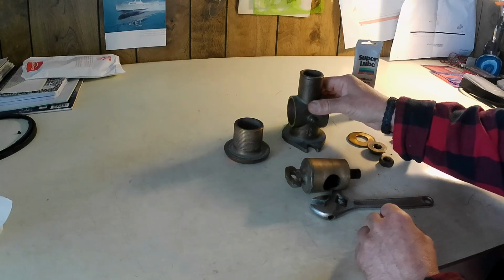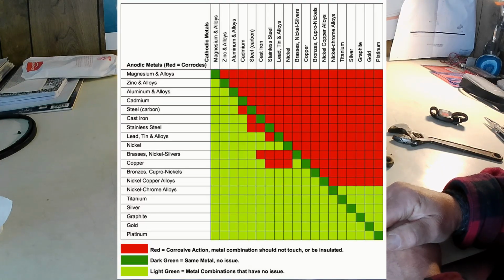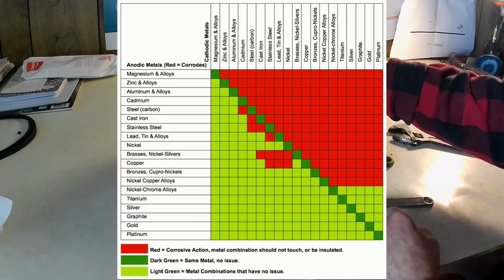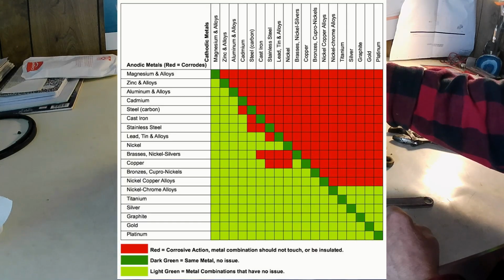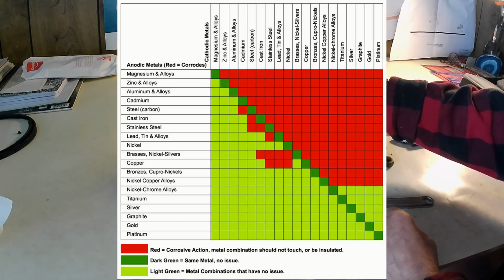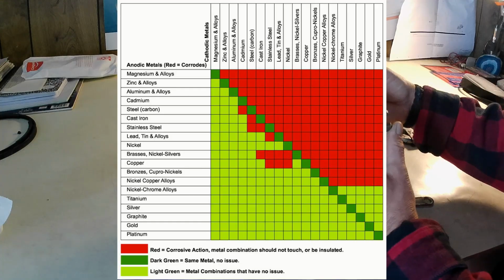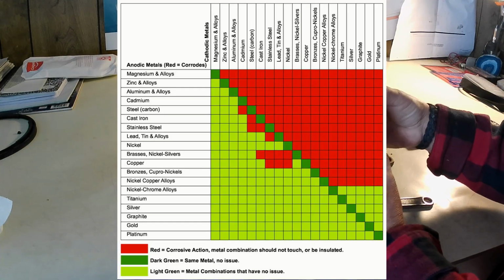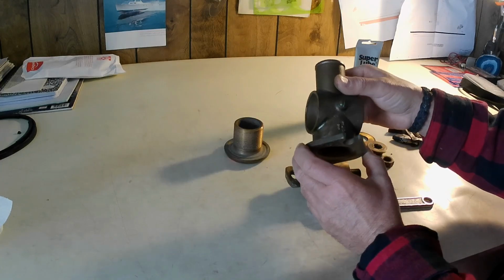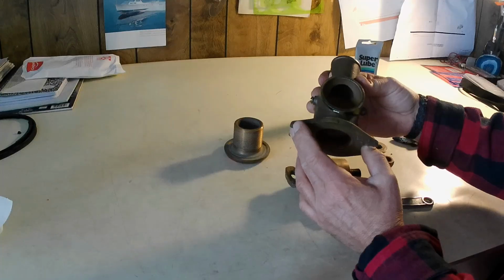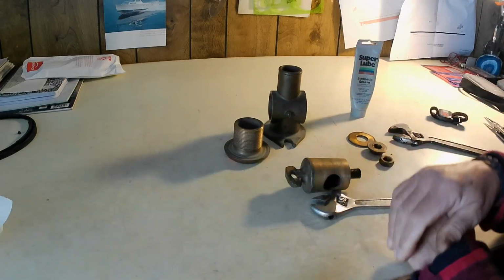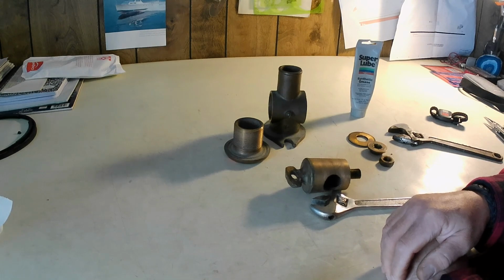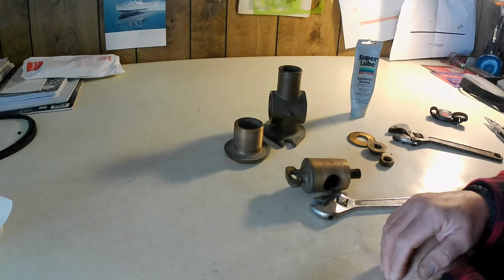Bronze, if you look at the galvanic table here, you'll see is generally not problematic in combination with stainless steel. And since you will likely have other fittings below the waterline that are a form of stainless steel, such as, for example, a prop shaft, bronze is the correct copper tin combination material to use with those in proximity. You do need to bond these. Bonding them means essentially electrically tying them together, and preferably tying them then to a sacrificial zinc or ground plane underwater.